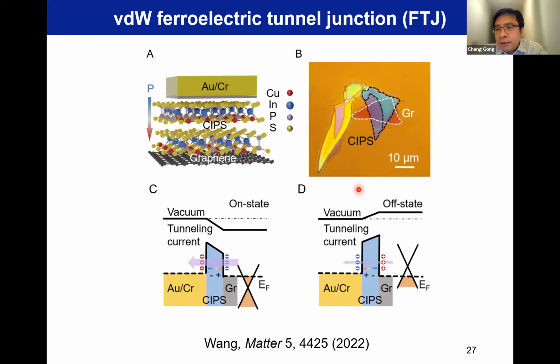So here is a piece of work. I focus on the development of 2D ferroelectrics. You can also use the traditional ferroelectrics for those kinds of visionary work. But many traditional oxide ferroelectrics, if you have them very thin, because right now you want to use small voltage, so you need to let the material be thin. The thickness times the coercive field is equal to the switching voltage. But when it is thin, many times the defects will cause substantial leakage current. So 2D ferroelectrics are potentially better in terms of electrical insulation with a minimum amount of defects.